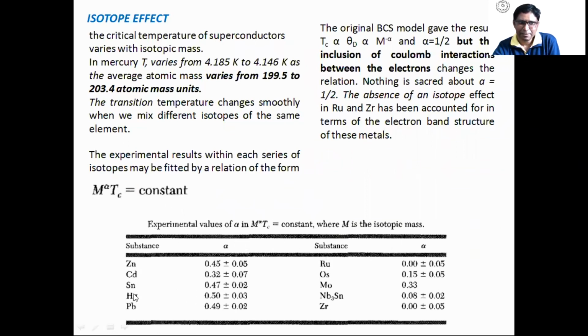For zinc, it is 0.45 plus or minus 0.05, and certainly it is equal to 1 by 2. Cadmium is equal to 0.32, it is around 0.4. Sn is 0.47, approximately 1 by 2. Hg is again 0.5, it is 1 by 2. Pb is 0.49, again 1 by 2. So experimentally you can say that alpha is equal to 1 by 2.